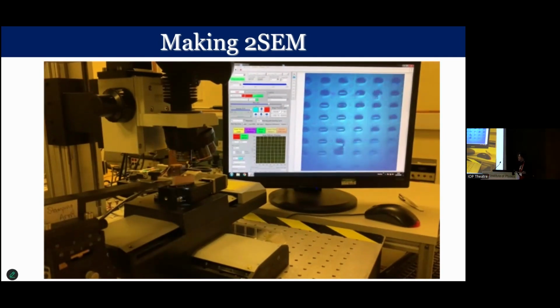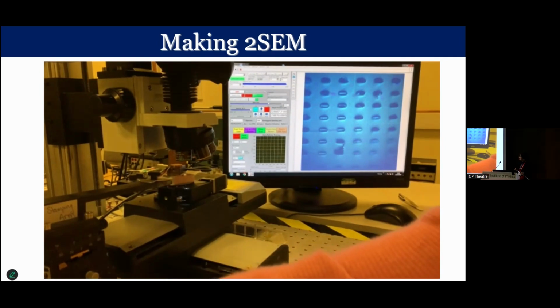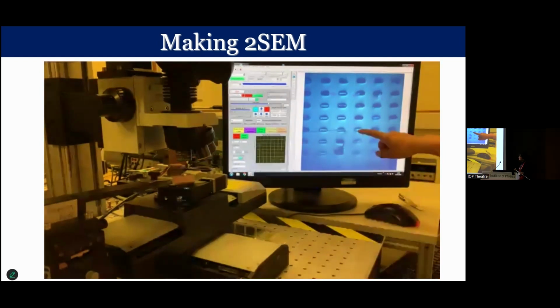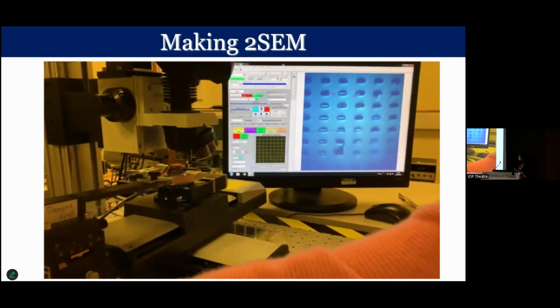As well as adjusting the height, the micro manipulators can be used to move the needle in the plane, so we can align the tip above a specific graphene strip. Once the strip has been selected, we bring the needle into contact, and we know this has happened because we can see a slight distortion in the surface. We then have to apply some pressure to the graphene to dislodge it from the surface.